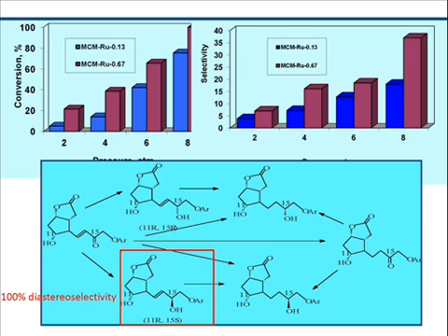But here we change the ruthenium precursor, and instead of normal inorganic compounds, we use ruthenocene. And we get the dispersion, which I already showed you, and the reduction oxidation for much smaller loading of the metals, and in such a way we achieved, I will show you, very good selectivity, 100% selectivity. So it was the first real example with smaller loading of the metals than usual, just on the fact that you assure the desired enantiomer selectivity.